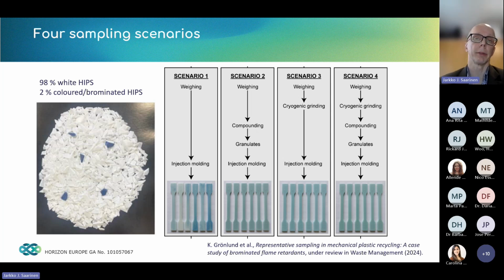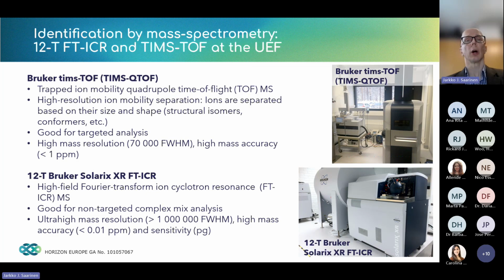the original peer-reviewed publication that is currently under review in Waste Management Journal. So, as we have seen in the case of scenario 1, just doing the injection molding is insufficient for guaranteeing an even distribution of the colorant throughout the dog bones. Once we do the compounding step in between, we see a significant improvement in the evenness of the samples. And the same story also for the cryogenically ground samples. We see that the density of the color is more or less even throughout these dog bones by means of visual inspection. So how do we do the actual quantification and characterization of these materials?